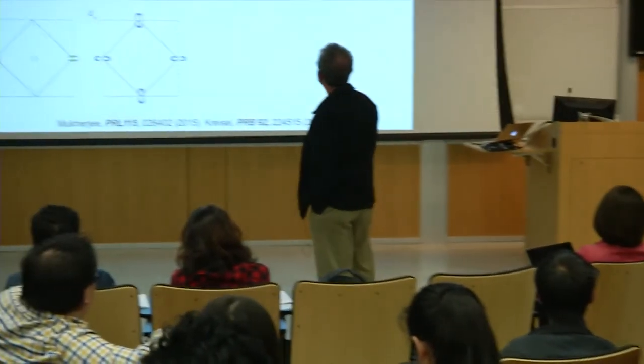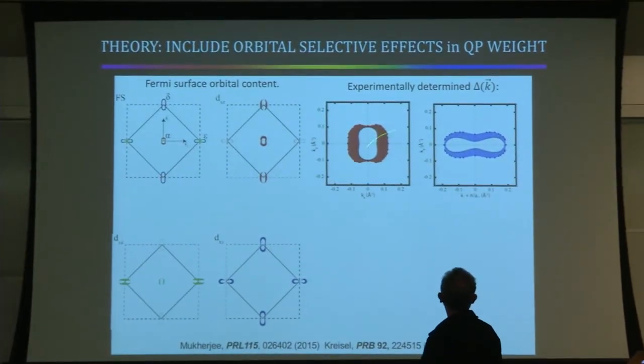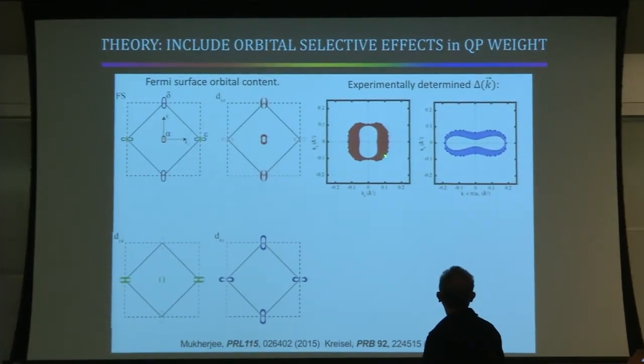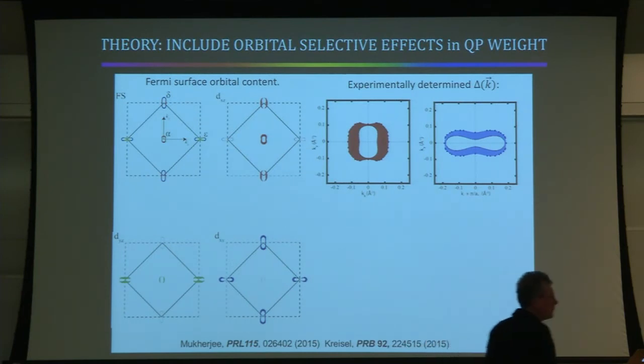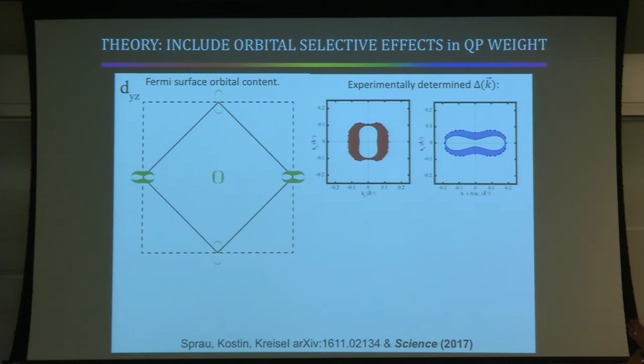All right. So, okay, look, we have these weird gaps. They change sign. They're on these tiny little pockets, and they're enormously anisotropic, but they have no nodes. It's a weird situation. One thing I noticed, I think my students might give me credit for this, but probably not, is that the orbital selective contribution to the Fermi surface from dyz was very like the gap structure. Here you have dyz orbitals. Here you have none. Here you have dyz orbital weight. Here you have none. That's an empirical fact.